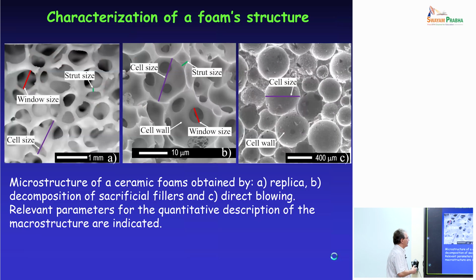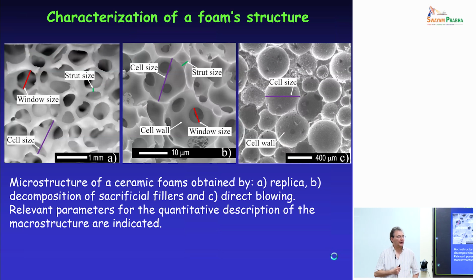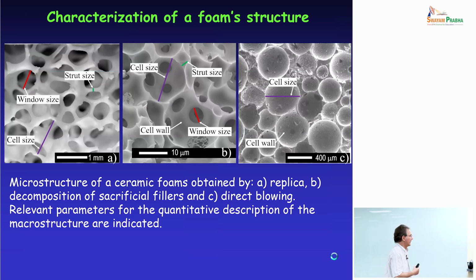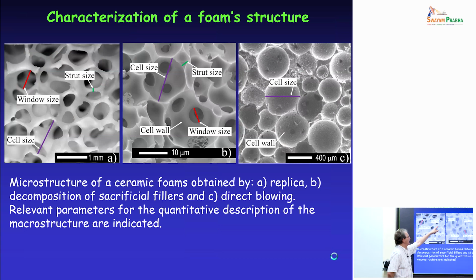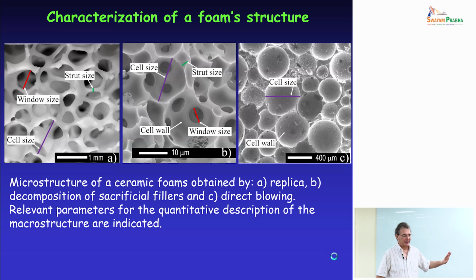You can see here two ceramic foams obtained using different materials. When you have a ceramic foam, you can characterize the morphology of the foam using different parameters. You can evaluate the so-called strut size, so the diameter of the solid constituent of the edges of the material. You can measure the cell size. And by the way, you can do computed tomography, but that is quite labor intensive. You can use optical or SEM images.